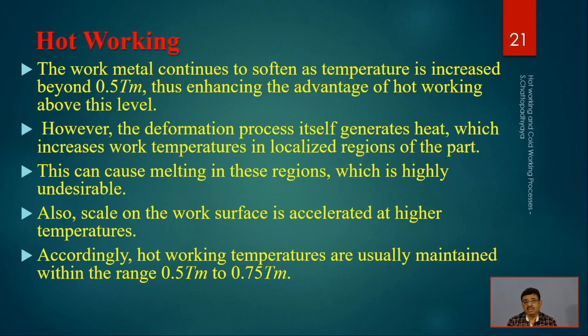So one has to be pretty cautious, because working also generates some heat, and scale on the work surface is accelerated at high temperature, obviously, because at elevated temperature the possibility of oxide formation is much more. Scaling is not desired; it will jeopardize the surface finish and also hamper the accuracy and precision of the products. Accordingly, the hot working temperature is usually within the range of 0.5 to 0.75 of the melting point of those metals.